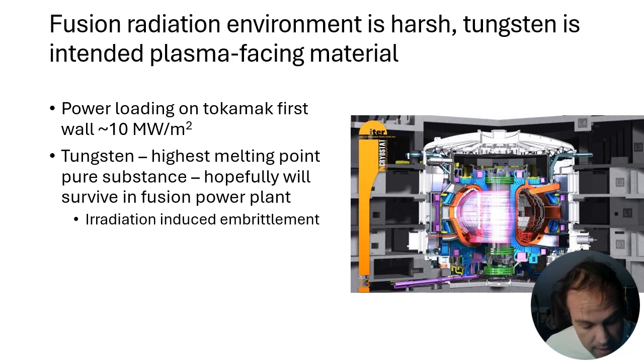So there's a number of problems with radiation damage to tungsten in the fusion context. One of them is irradiation embrittlement. Power loading is going to be very high. There's going to be thermal stress on the first wall components. So if we build these inner walls out of tungsten, and if they see this power loading up to 10 megawatts per meter squared, that is like enough to vaporize almost, well, maybe anything. So they're going to have to deal with these extreme thermal stresses, and radiation-induced embrittlement could be a deal breaker for this component.